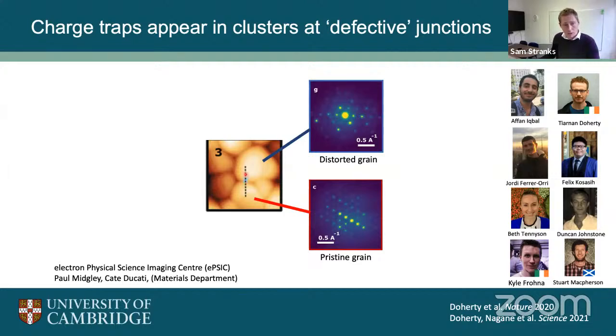And we can look at the crystal structure of these grains. If we look at the crystal structure of the grains on either side, you can see that the grain on the bottom there is pristine. When we send electrons through and look at the diffraction pattern, how these electrons interact with the material, we can tell what the crystal structure is of these different regions. On the bottom there, it's a pristine grain, so it's the perovskite that we would expect. But on the top there, that pattern is slightly distorted. So we have a grain that's more defective, and it's at that junction where these carrier traps form. They form in clusters.